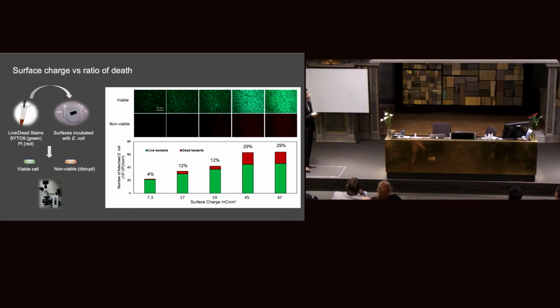Therefore, we can see that the red signal here shows the bacteria has a disrupted membrane, while green means the bacteria still has an intact cell membrane. So we can see with the increase of charge, the bacterial amount increased, and also the dead ratio increased from 4% to around 30%.